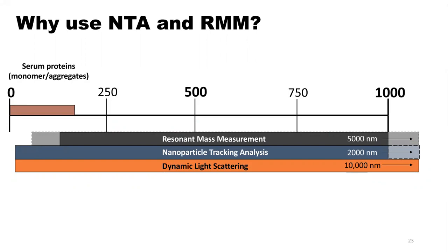But surely the same thing happens with NTA. The size limit at the bottom end is the same. And it looks like that, but what you're able to do with nanoparticle tracking analysis is tell it what are the things you're interested in, so in this case the PLGA nanoparticles, and tell it to effectively ignore anything else, so that would be all the unbound protein. And resonant mass measurements, on the other hand, with the settings that we particularly use, the bottom end of its size limit is almost set so high that it can't even see any monomeric proteins.